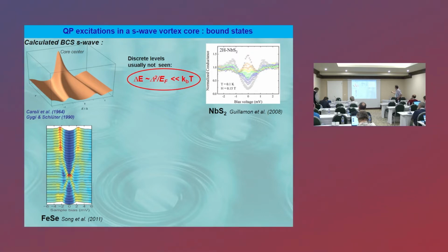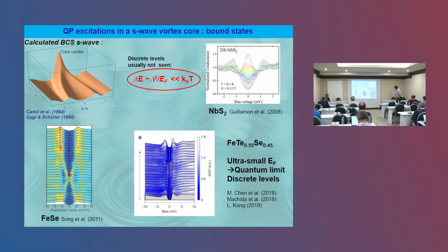And so this has been observed in many cases of S-wave superconductors, like niobium disulfide or diselenide, or the iron-based superconductor, where you see that the center of the vortex is associated with a zero bias anomaly. And while going away from the center of the vortex core, this central peak splits into a set of two peaks due to the increasing angular momenta. And then the splitting is seen by these STM measurements. But as I told you, the individual states cannot be seen in conventional S-wave superconductors until quite recently, where, for the reason that the Fermi level is very small in this compound, iron tellurium selenide, EF is very small, so the spacing was large enough to be detected. So the first localized state was detected in that kind of compound. But this is not very often the case.